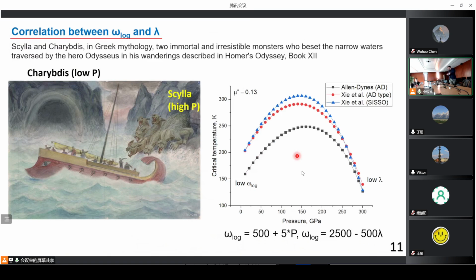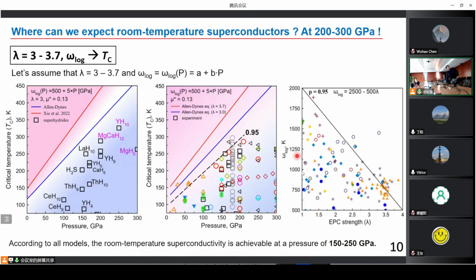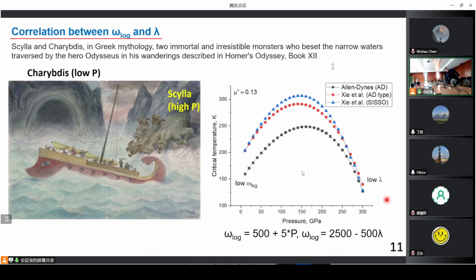Actually, it's not only one case of superconducting hydride. We have two parameters: logarithmic frequency and lambda. When lambda increases, TC increases, but at the same time the logarithmic frequency decreases statistically, and again TC decreases. So the final result is parabolic. It's more like a compensation through the logarithmic frequency. I see. Exactly. Interesting. Between hydrides and Scylla, you need to pass between these two monsters.